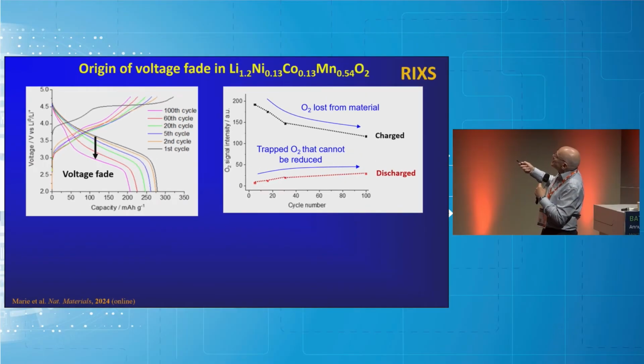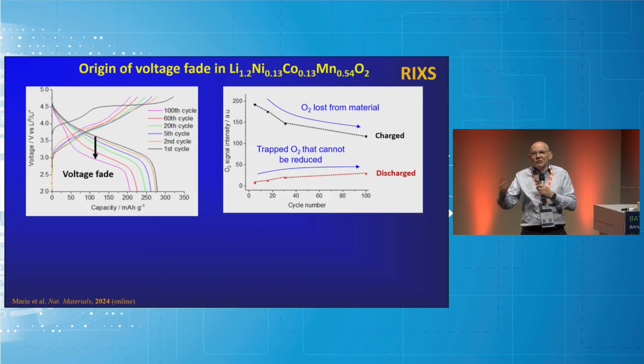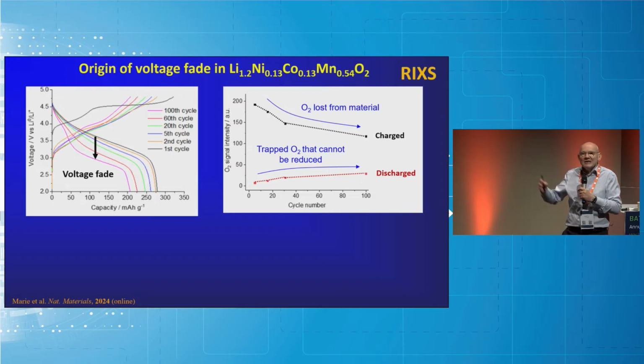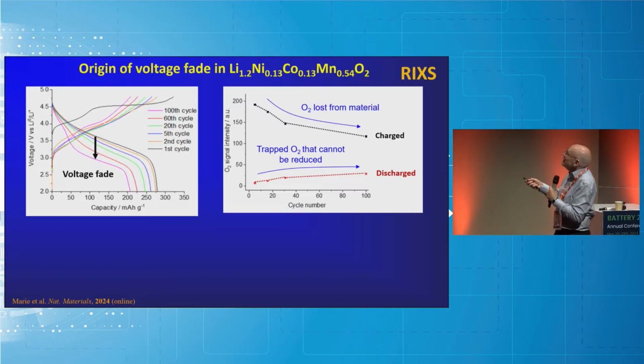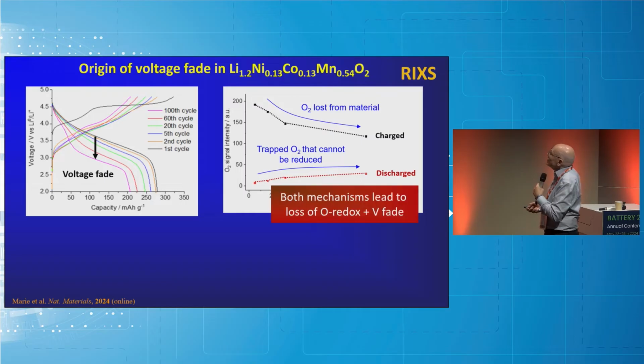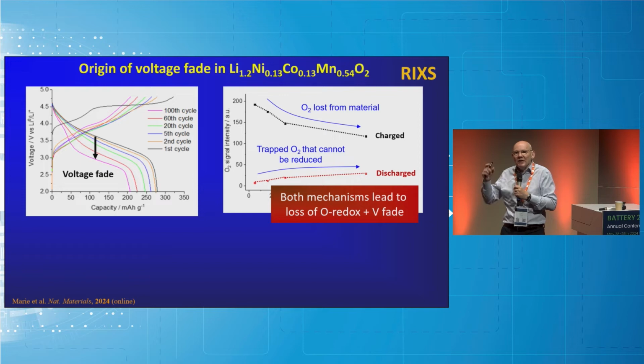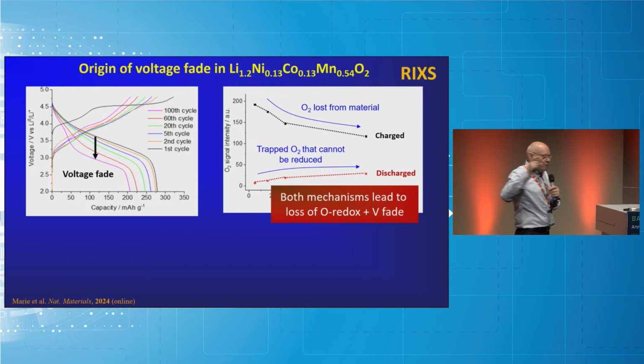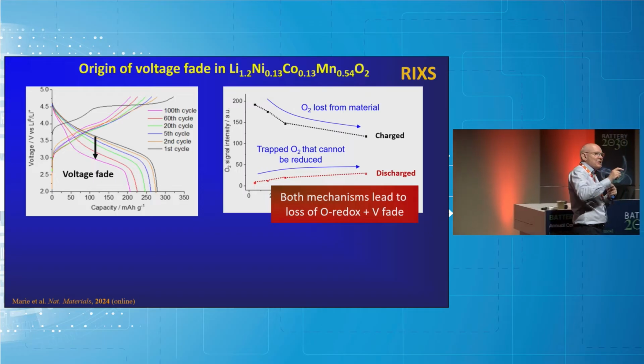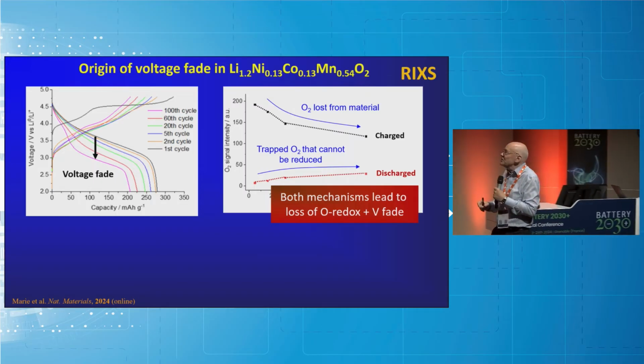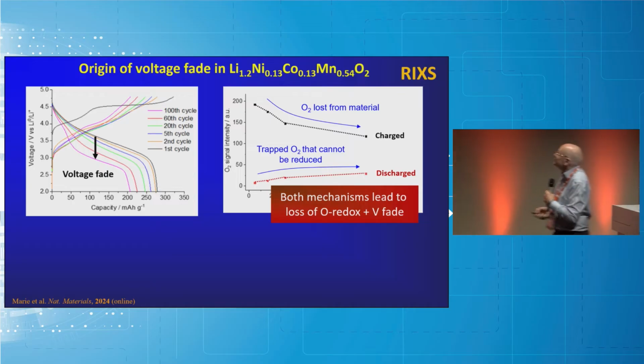The thing that really surprised us was that you can actually see O2 trapped at the end of discharge. Now, at the first cycle, I showed you all the O2 goes back to oxide ions. But gradually, as you cycle and cycle, some of that O2 is never reduced again back to oxide ions. It becomes stuck and accumulated in the structure. Both these mechanisms lead to voltage fade because they're removing oxygen redox, which is a relatively high voltage process, and replacing it to some extent with transition metal redox, which is lower voltage. And that's what causes the slippage of the voltage.